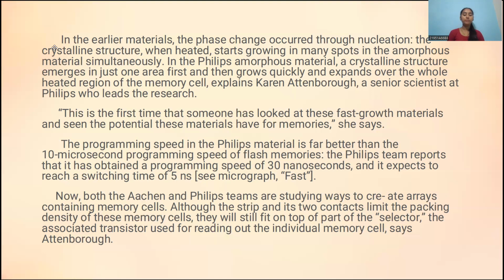She says the programming speed in these Philips materials is far better than the 10 microsecond programming speed of flash memories. The Philips team reports that it has obtained a programming speed of 30 nanoseconds and it expects to reach a switch time of 5 ns.